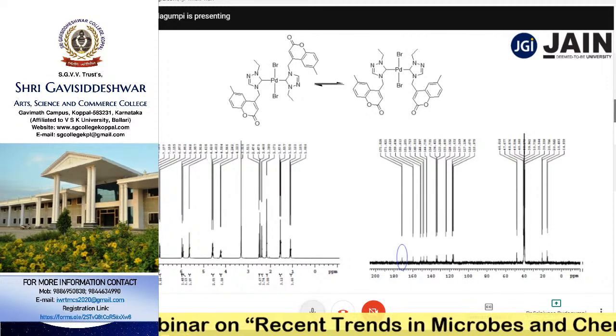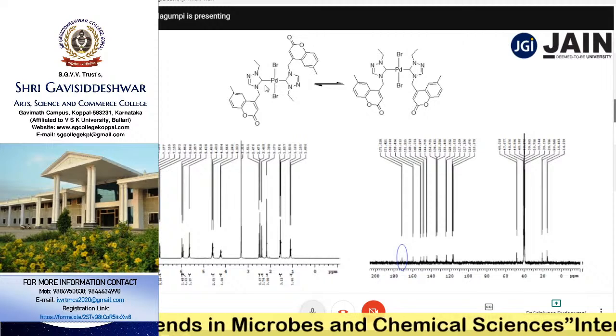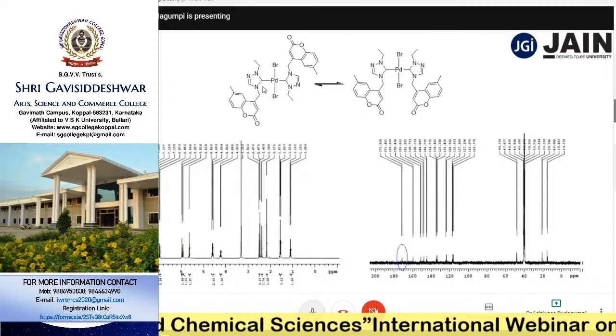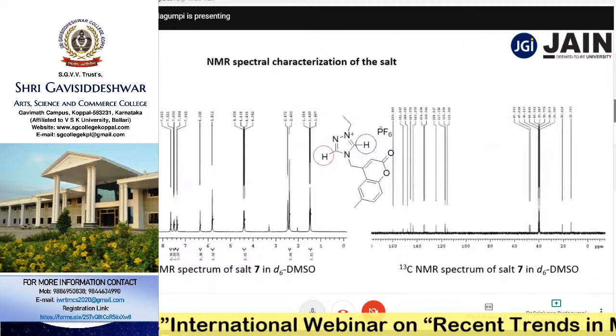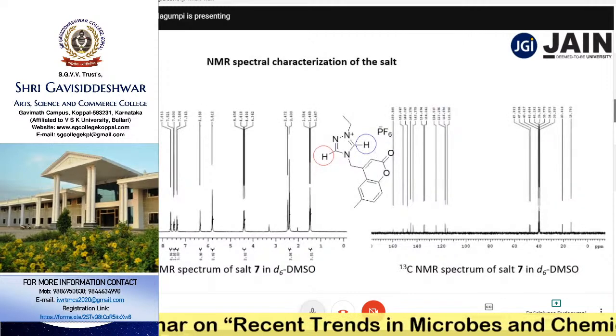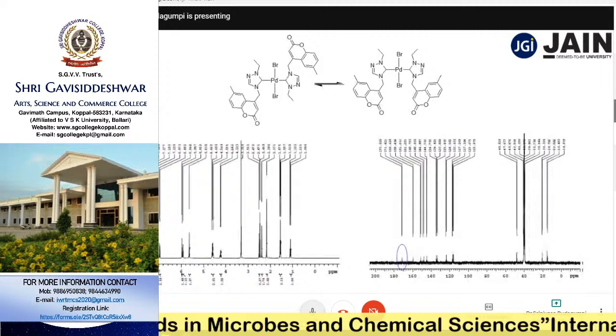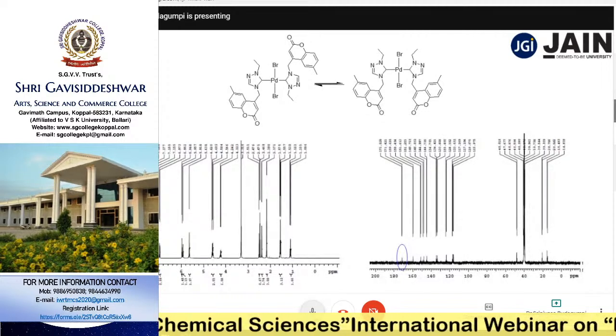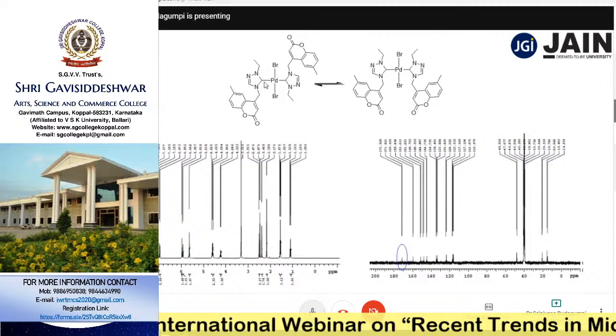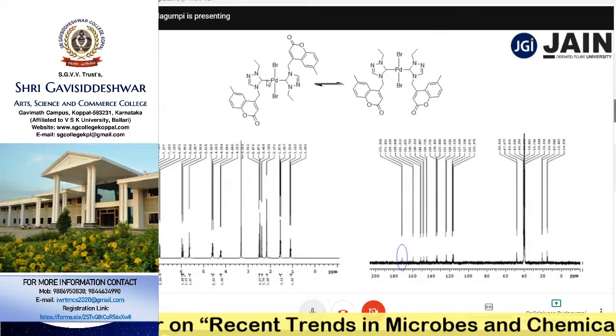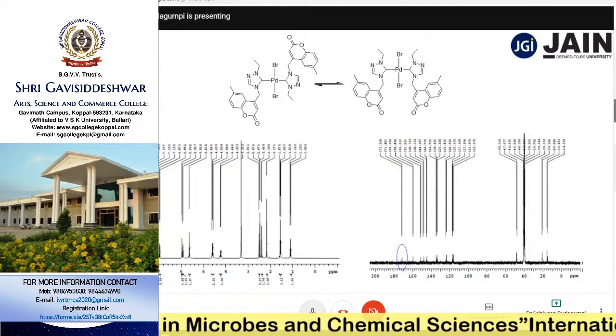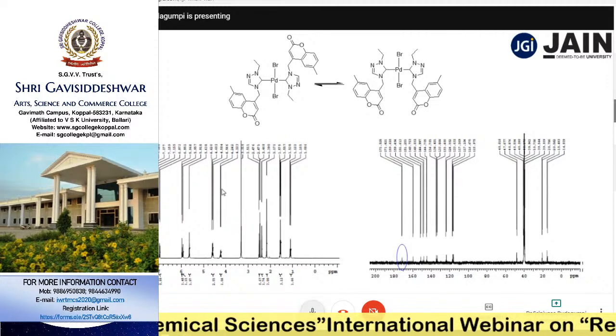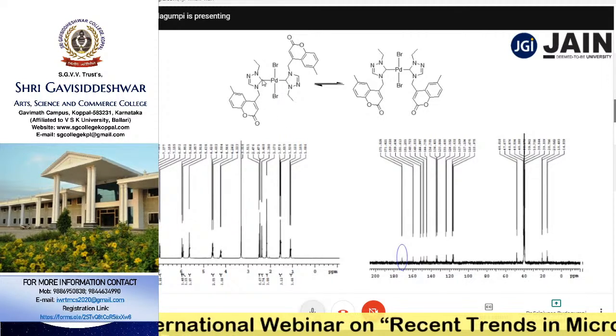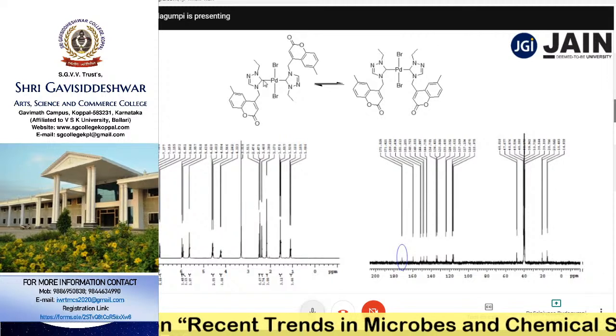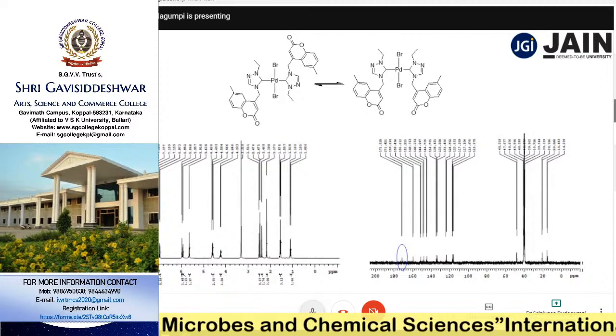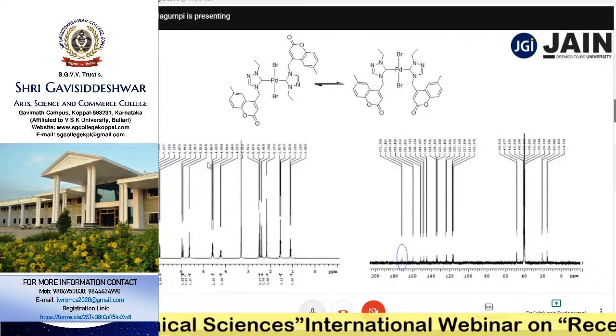So in the proton NMR spectrum of this particular complex, there is no peak corresponding to the C5 proton. See, this is the C5 proton that appeared at 10.1, whereas in the complex there is no proton appearing at 10, indicating that this proton is deprotonated and the carbene is generated, which is trapped by the metal center. So that is how we can isolate it. That is the inference we can draw from this NMR spectrum. The C5 proton is deprotonated, and through deprotonation a carbene is generated. That deprotonation is evident here. There is no proton resonance at 10 ppm.